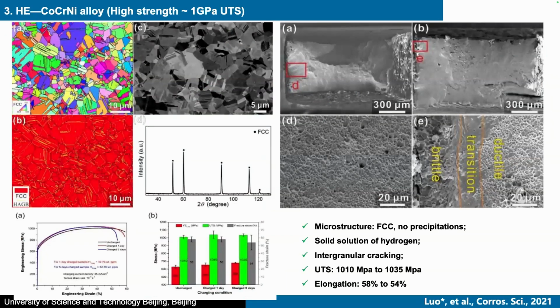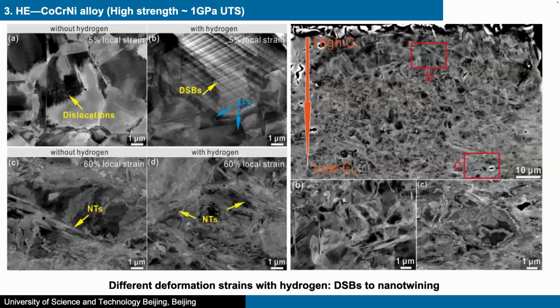Its UTS is about 1000 megapascal. It's also a very stable FCC, no precipitation. And we did a similar experiment and found the surface is slightly brittle, and also has transition regions, and also ductile sites. And we observed the deformation microstructure with different local strains.